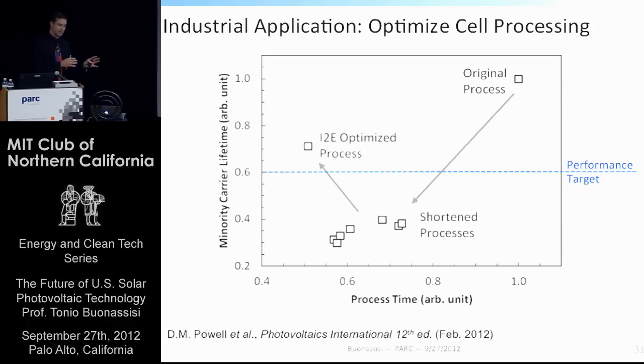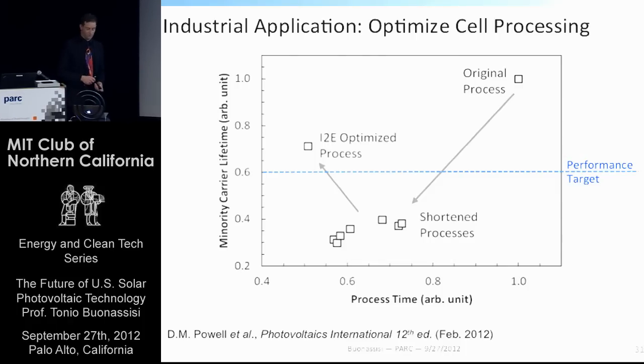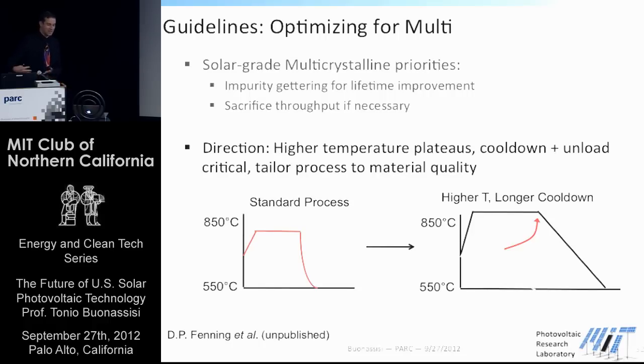So it's an exciting application of a project that started as a DOE-funded research and eventually worked its way into industry. Likewise, if you have another input material, so-called multicrystalline silicon, your process might look a little different. Instead of using a high-temperature short process, you might use a longer time step at higher temperatures to dissolve precipitates and then cool down more slowly to room temperature to manage the collection of impurity point defects. And even though you've increased your total cycle time, the efficiency improvement more than pays for itself. So that's where the cost model comes in handy, because now we can figure out, aha, we double our process time. What percentage improvement of efficiency do we need to achieve to overcome the additional cost of added process time? We can begin quantifying that now.